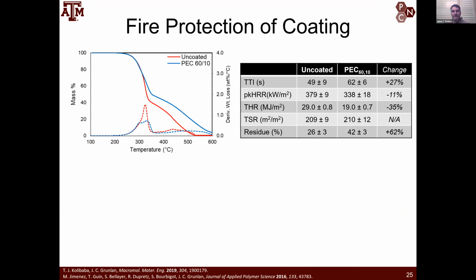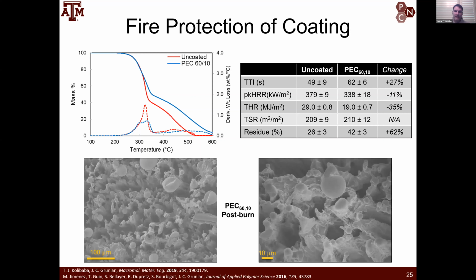And so here we're looking at TGA, or actually micro-cone calorimetry, which is a lot like a TGA. And you can see time to ignition, peak heat release rate, total heat release, total smoke release, etc. And if we compare uncoated and coated, you can see time to ignition takes longer, peak heat release rate is reduced, total heat release is reduced, and the residue goes up dramatically because of this coating.